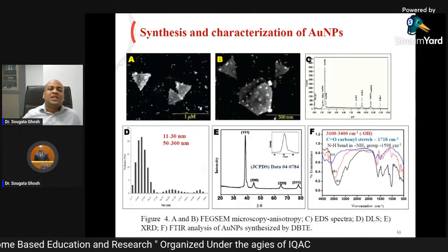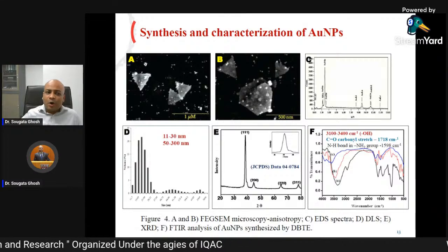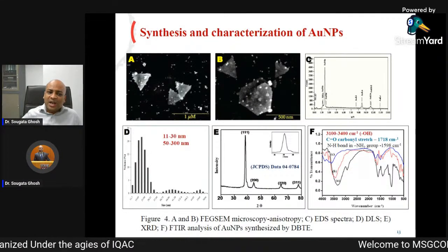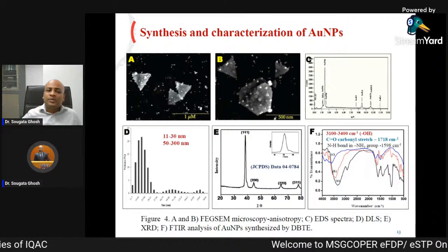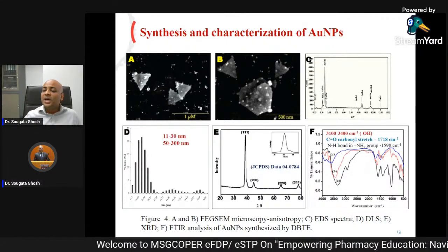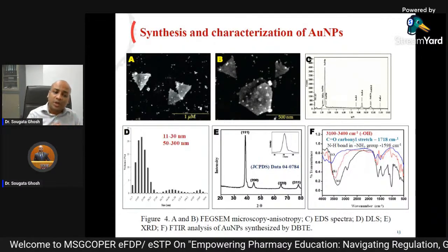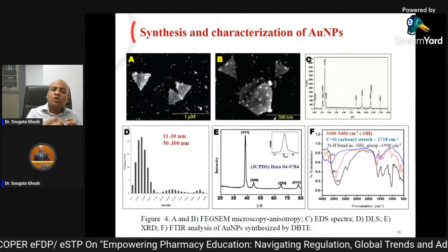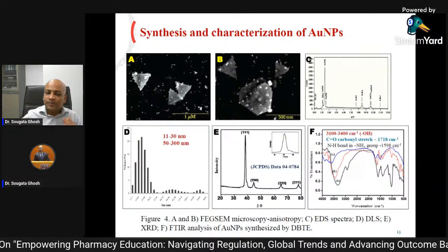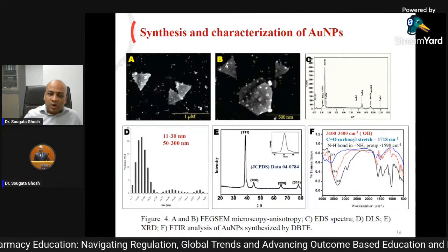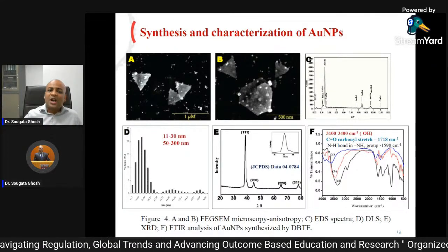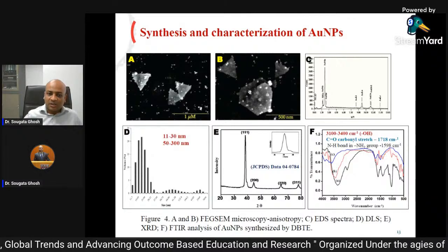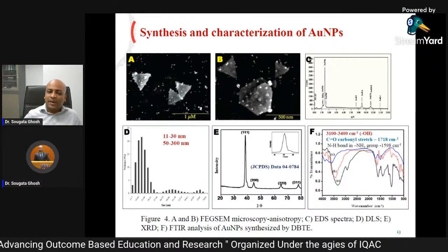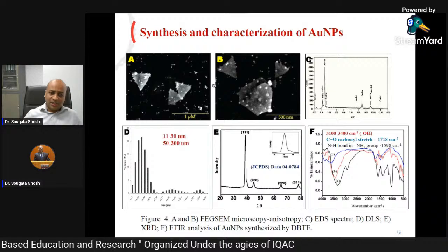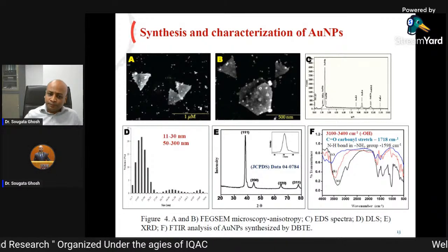Next, we wanted to see what is the shape and what is the size of these gold nanoparticles. So we found that these gold nanoparticles initially formed were very small spherical nanoparticles. They were coming to form smaller triangles, and then aggregating to form bigger triangles. So there is a shape evolution, very small to bigger and then much bigger. Similarly, there were smaller spherical nanoparticles, triangular nanoparticles, and hexagonal nanoparticles. So this is FESEM, field emission scanning electron microscopy.